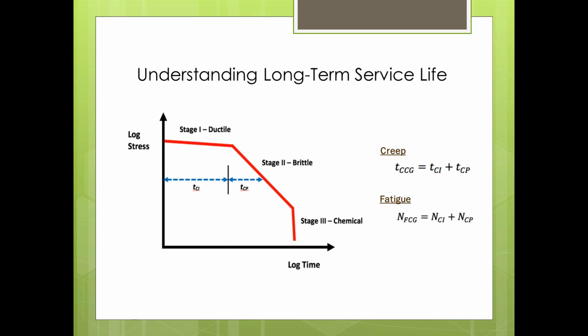That stage is very appropriate, especially when you're looking at pressure pipe applications. A lot of the solid wall HDPE pipe that's designed for water main is designed to handle some of those very high internal pressures and stress levels that are placed on the pipe wall. And when they do the burst testing via ASTM standards, it's really geared towards understanding that first stage failure and making sure that you're designing it so that that stage one failure doesn't happen in the field.